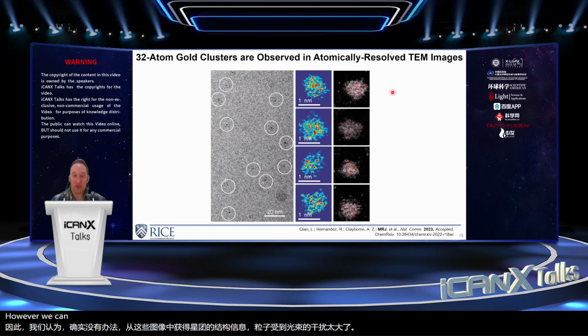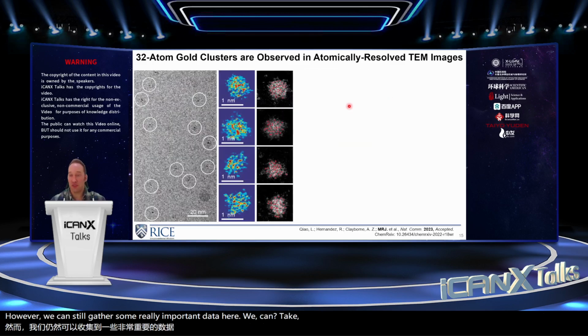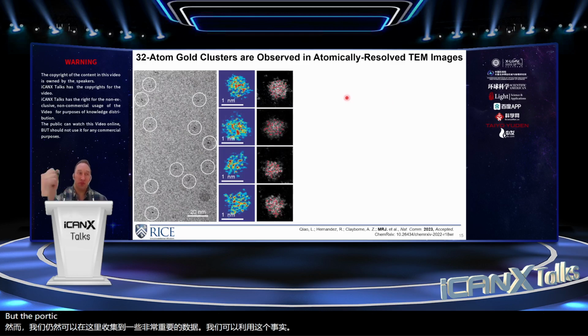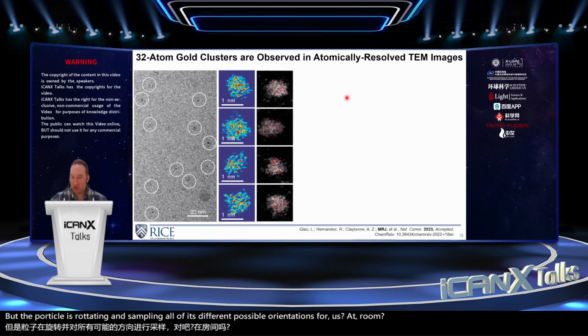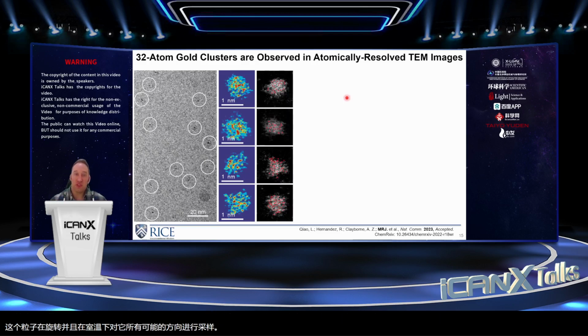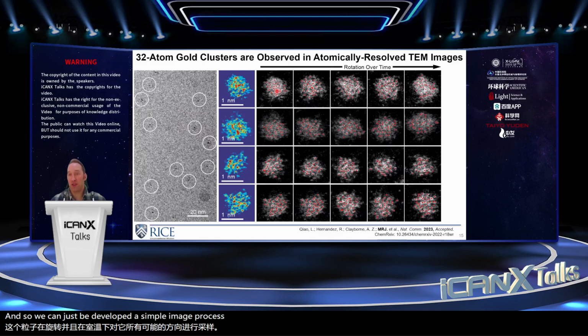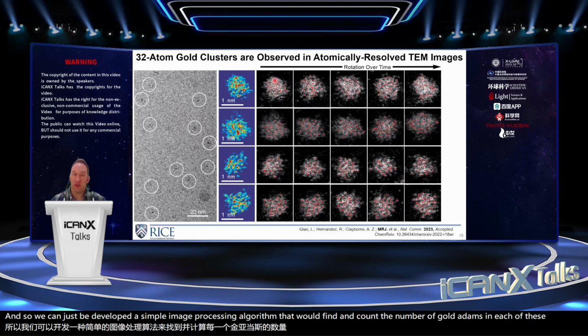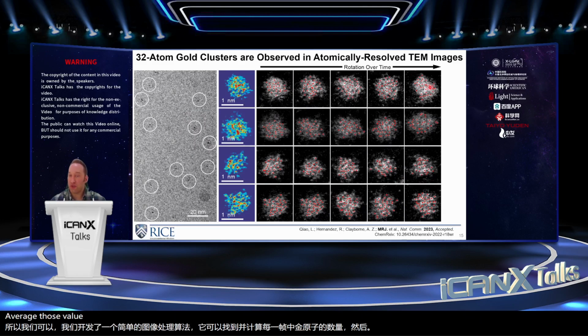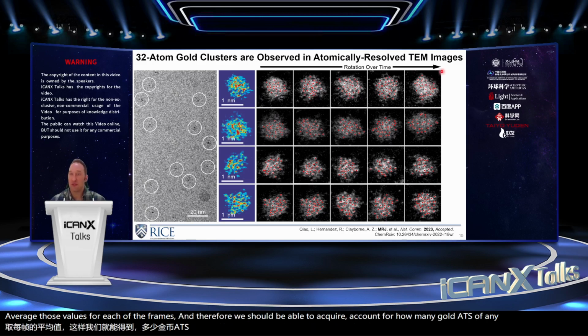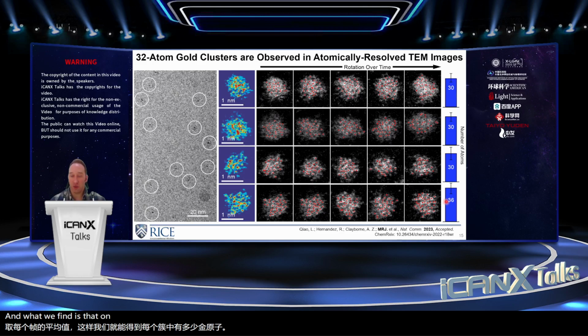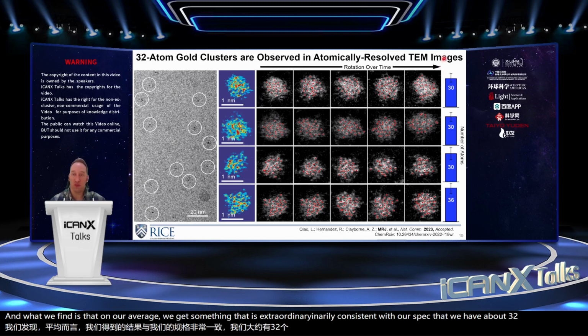However, we can still gather some really important data here. We can take advantage of the fact that the particle is rotating and sampling all of its different possible orientations for us at room temperature on its own. And so we developed a simple image processing algorithm that would find and count the number of gold atoms in each of these frames, and then just average those values. Therefore, we should be able to acquire a count for how many gold atoms are in each cluster. And what we find is that on average, we get something that is extraordinarily consistent with our mass spec data, that we have about 32 atoms per cluster.